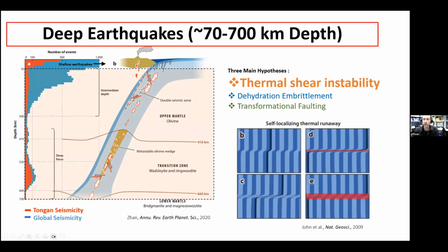One is a thermal shear instability. So basically, you're straining the rock, it heats up frictionally, which softens the material, which leads to more strain, which leads to more heating, and you end up with a runaway, which is what they're trying to show in this simulation at the bottom here, and the red is melting. So eventually you get a melt band to form, and you can slip along that.